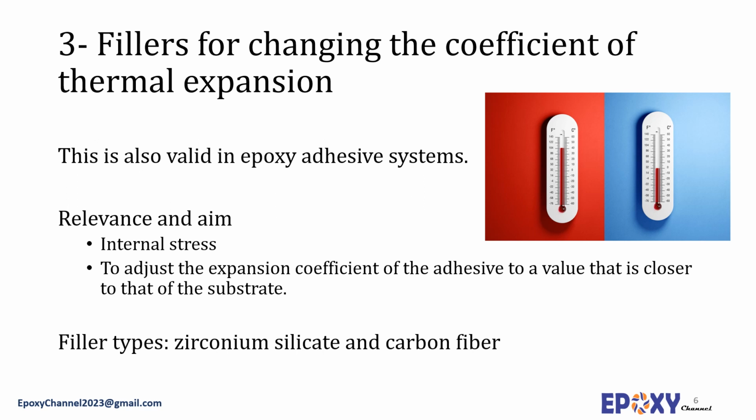the expansion mismatch problem. However, the creep of the adhesive is possible here, and also highly deformable adhesives usually have low cohesive strength. Another approach is to adjust the expansion coefficient of the adhesives to a value that is closer to that of the substrate. This is generally accomplished by incorporating specific fillers to tailor the thermal expansion coefficient. Often the reduction in coefficient of thermal expansion of the cured epoxy resin is proportional to the filler's degree of loading.